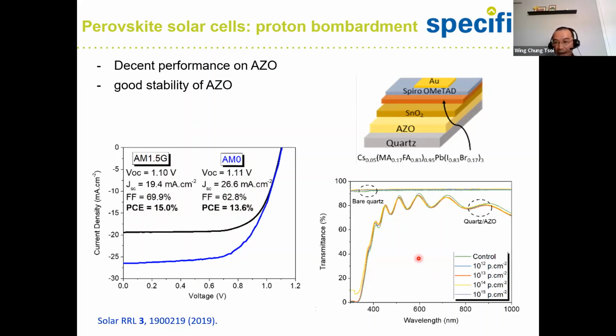And then we bombard the material with protons with energy of about 150 kilo electron volt with different fluence, which means the number of particles per centimeter square. This is the optical transmittance spectrum of the bare quartz and with the AZO. You can see they're very similar, even up to the highest proton fluence. So it is consistent that the AZO electrode we used here is pretty proton stable. For more detail, you can find it in this publication.